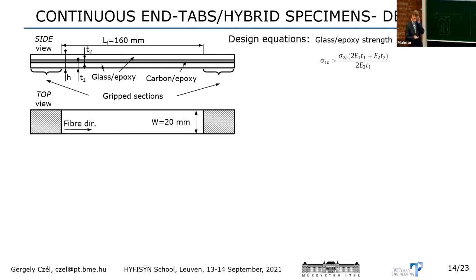So there are some simple design equations. One is that we want to keep the glass layers intact when the carbon layer fractures. It is for the stability of the test, for good detection of the fracture point, and so on. It's actually mainly for convenience. So we could even get good results if we make sure that it is not the glass plies which trigger failure, but if we fail the carbon and the glass fails immediately after, that could still be fine.